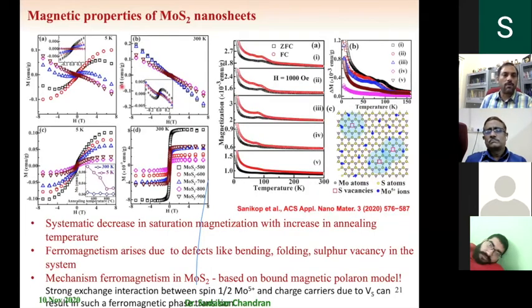And that's what we found here. So here we have shown with defects, that means 500 to 900, how the magnetic properties change. You can see that 500 annealed samples exhibit high magnetization. As you increase, they become low. In fact, they become diamagnetic in nature.